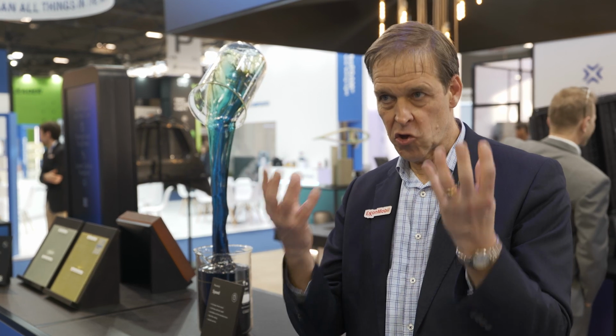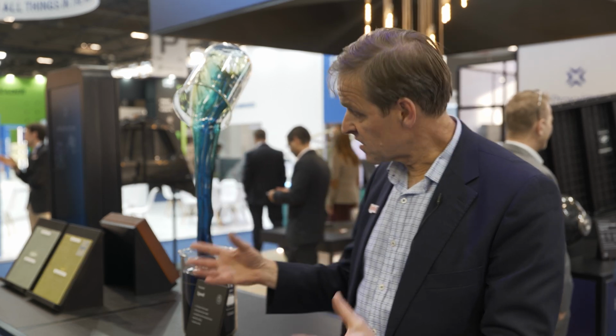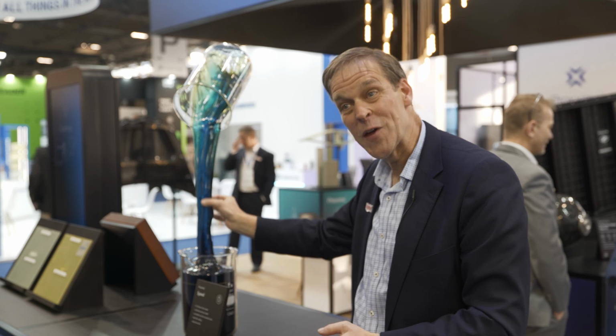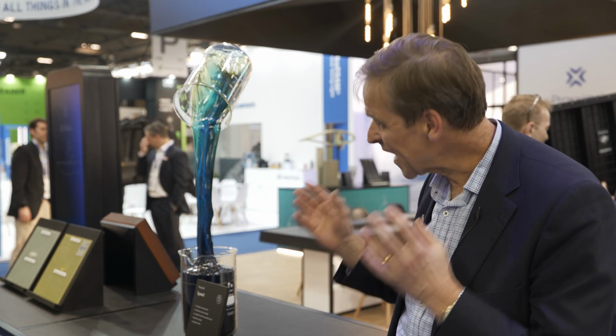If you look at what Proxxima is, it's a liquid thermoset. So it's a two-part system of two liquids, right? Both liquids have the viscosity of water, so 20 centipoise. And what we do is we mix those two liquids, and then the catalyst sets off and cures and makes a solid. I like this example because literally what we've done is we put the two things together in a beaker, gone 1, 2, 3, 4, 5, and it's a snap cure. So literally we are freezing the water, curing the water in this way. There's no trick to this. That is the way it was made. So we have the ability to have this snap cure.